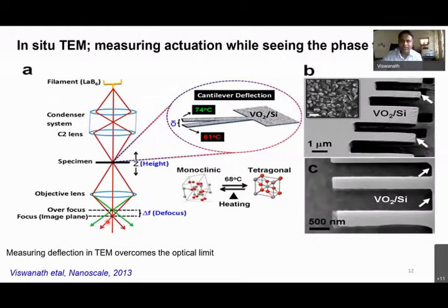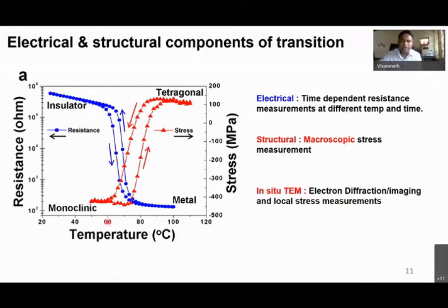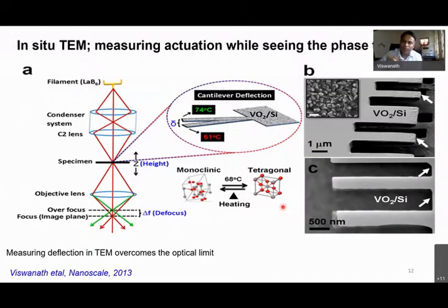So the question here is, I told you earlier that with wafer curvature, thin film stress can be measured. But can we use in situ TEM during heating inside the transmission electron microscope? When I record an electron diffraction pattern and a bright field image, can I also try to visualize the phase transformation induced actuation? So we have tried this particular method. In fact, initially I was not very sure. At least in my understanding, it is the first time we have used the TEM to get the actuation.